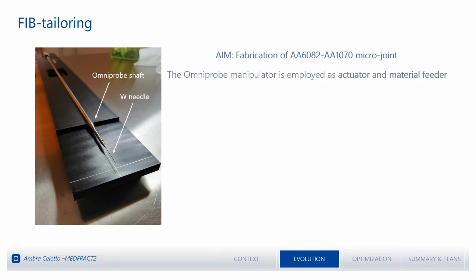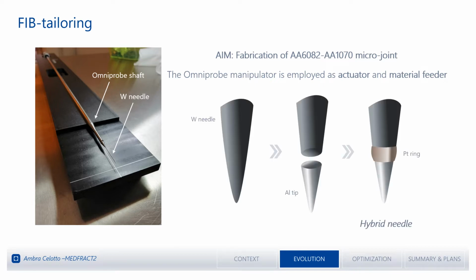We can feed this material, our aluminium alloy, by replacing the needle's tip. So we take the tungsten needle, cut its tip, replace it with an aluminium tip, and secure it with a robust ring of platinum deposited by the gas injection system. In this way, we get a hybrid needle that will feed this material on its tip.